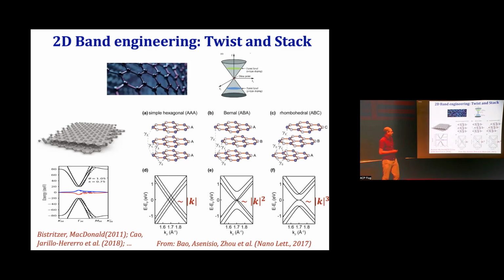Now, let me also mention, I'm treating this stacking degree of freedom as if it's completely our choice. Of course, there's only one of these structures, which is the ground state of 3 layers of graphene, and that's this one. That's Bernal-stacked graphene. That's the lowest energy state. But the other ones are metastable states. You can create them in the lab. It's challenging, but people have been able to do this.